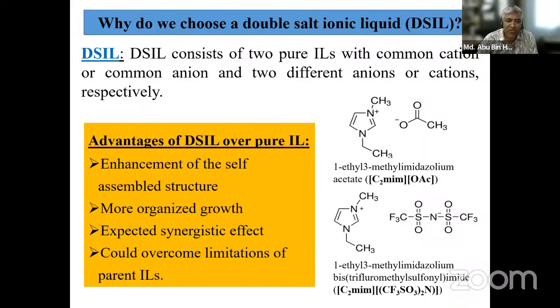So the advantage of double salt ionic liquid over pure ionic liquid is the enhancement of the self-assembled structure, which can be controlled, and it can be more organized for the growth profile, with an expected synergistic effect. Two anions may collectively give some synergism in the properties, and they may overcome limitations of the parent ionic liquid. We shall shortly see how these have really been achieved.